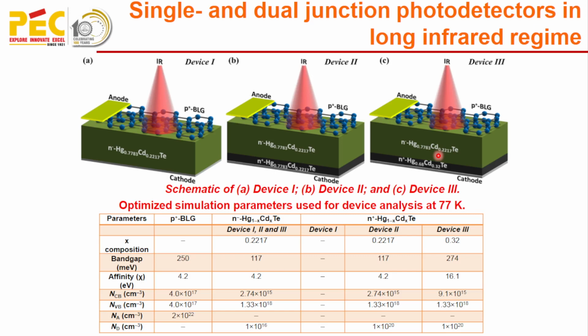highly doped layer was optimized so as to increase the built-in electric field at the junction, and this built-in electric field will drift the photogenerated carriers to the electrode, resulting in effective photocurrent through the heterojunction. So for all the three devices, device 1, device 2 and device 3, the energy band gap, mercury cadmium telluride composition and thickness of the active layer have been optimized for the best compromise between the requirement for the efficient use of the LWIR radiation and low thermal generation.